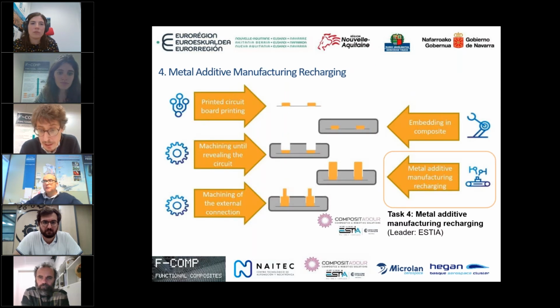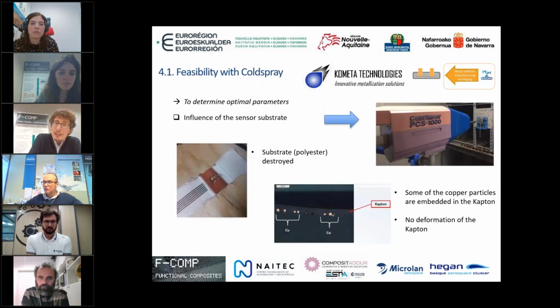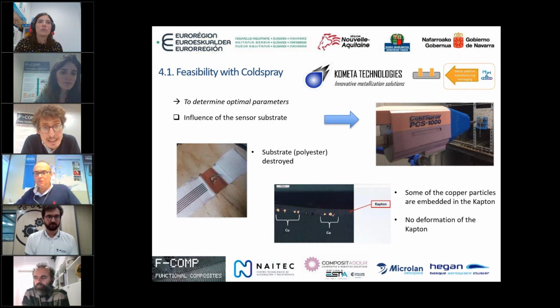The fourth point is, with this part revealed, adding recharging material to the sensor. This is as well led by COMPOSITADOUR, and they have in their own facilities the company called Kometa Technologies, who are experts in doing this kind of metallization. And in this case, the process has been as well a bit iterative. First, we saw what was the influence of the substrate when applying the process. In this case, the process is quite aggressive. So we saw that the polyester substrates were completely destroyed, in the photo on the left. There was some copper in the substrate, in the Kapton a little bit more, but not too much.